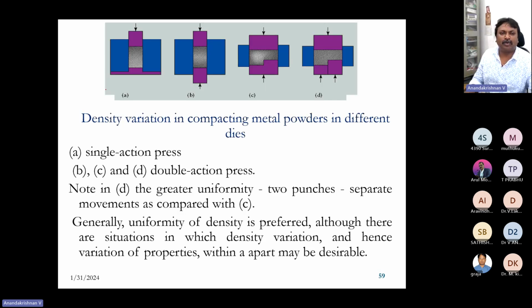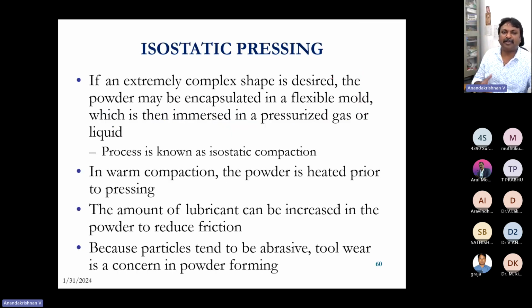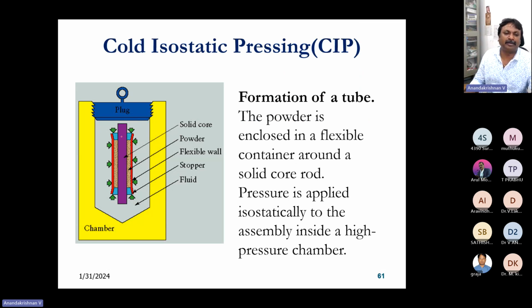And this is how different die movements, punch and die systems, can help. In this case, see here, there are 3 moving parts. This kind of die design can help create an almost uniform, homogeneous distribution of particles, so that we will not have porosity located somewhere. For that, you can go for isostatic pressing. You can put it in a chamber and apply pressure all around, and now we can fill the powder.